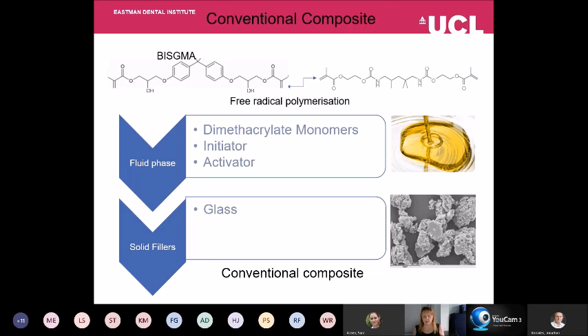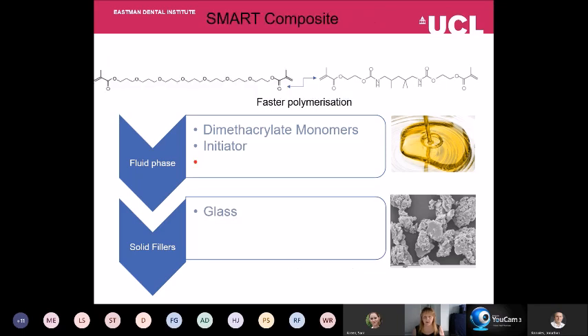If we look at a conventional composite, it consists of around about 20% of dimethacrylate monomers with an initiator and an activator in there. The monomer is usually bis-GMA. The problem with bis-GMA is it's got a couple of benzene rings in the middle of the structure. That makes it a very rigid molecule, and that can slow down its ability to polymerize. To solve that issue, what we've been doing is removing the bis-GMA and replacing it with a much more flexible molecule. What this allows us to have is much faster polymerization and more extensive polymerization. It also means that we can take out the activator that was in the conventional composite, which is known to be cytotoxic.